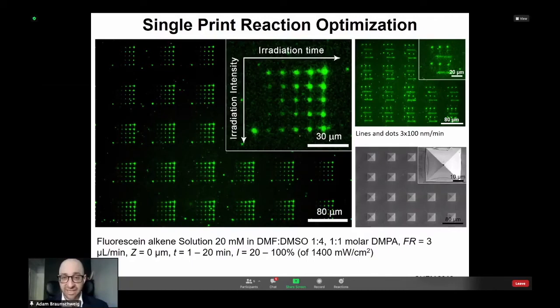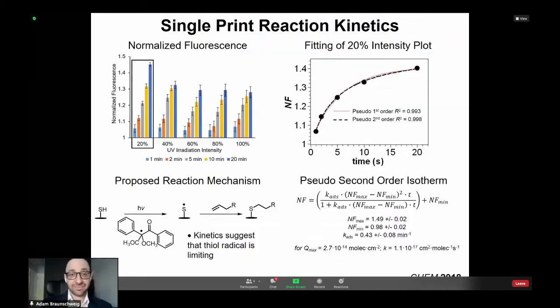And this just points to the importance of being able to do reactions in parallel, high throughput. Because if this reaction doesn't work, your initial thought as a chemist would be, okay, crank up the light intensity. But what these data are showing us is that's actually going to lead to a failure. Only with the ability to try so many different conditions were we able to figure this out quickly. And then in addition, having all those data points, what we could do is quantify the kinetics of the surface reaction with just data gathered in a single afternoon.